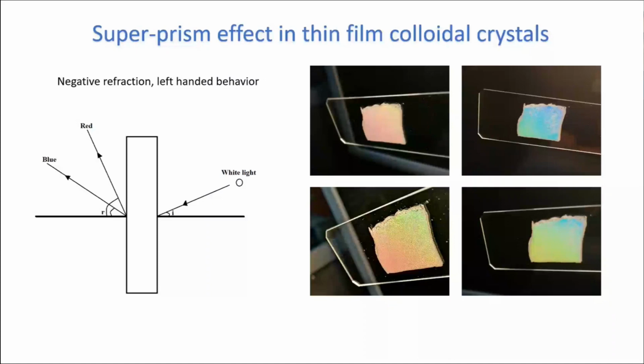And this is the left-handed behavior of such materials. The light is not refracted in the classical angle, in the classical plane. What is remarkable is that it gives, by transmission, a highly intense light. It is used, or at least proposed to be used, in modern spectrophotometers, because, compared to the classical glass prism used for dispersion of the light at some angle, this disperses the white light at a much, much larger angle than a classical prism, and in addition can be miniaturized.